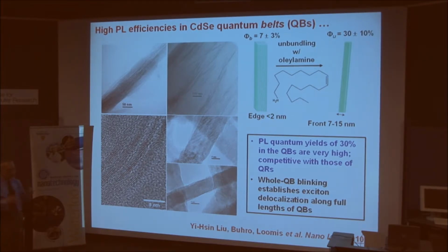We can then unbundle the belts by sonicating these bundles in the presence of a long chain amine, and the bundles come apart. And now we can see the broad top and bottom faces of the belts. And we can see that they're on the order of 7 to 15 nanometers wide, and on the order of 1 micrometer long, which is much shorter than the wires that we can make by the SLS method, but that's reasonably long in comparison to the exciton dimension.